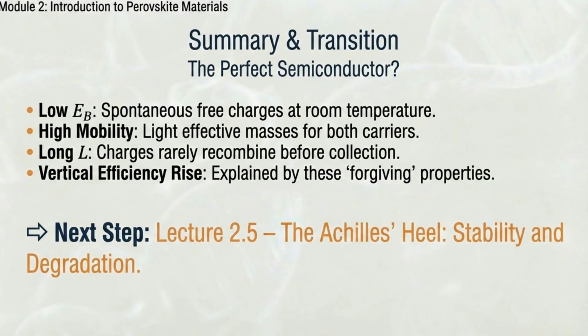Let us summarize the physical picture we have built today. We can now fully understand why perovskites are often referred to as a miracle semiconductor. They combine a rare suite of advantages. First, massive dielectric screening crushes the exciton binding energy, enabling the spontaneous generation of free charges at room temperature. Second, optimal orbital overlaps create incredibly light effective masses, resulting in high-speed ambipolar mobility. Third, defect tolerance extends the carrier lifetime, yielding extreme diffusion lengths.